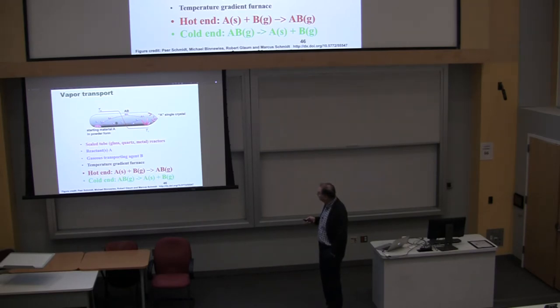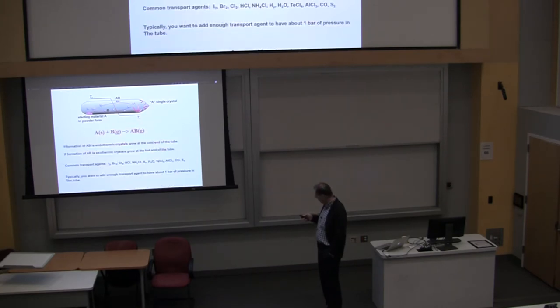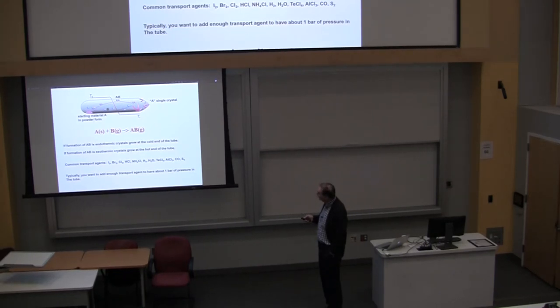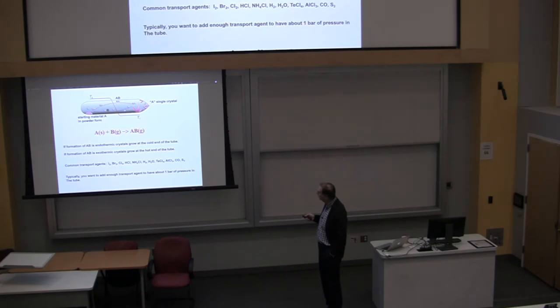There's a reaction, A plus B goes to AB. The idea is that you have one side at T2, a hot side, and a cold side, and the reaction proceeds, so you have an equilibrium. When you have a temperature gradient, the Le Chatelier principle essentially says that if your reaction is endothermic, your crystals will grow at the cold end of the tube. And if the reaction is exothermic, crystals will grow at the hot end of the tube.